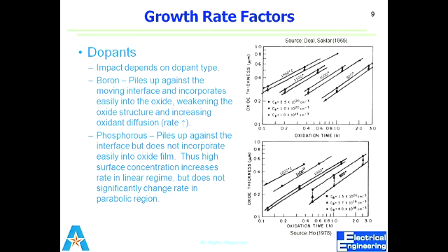In the case of dopants, you will find there are more non-bridging oxygen atoms. Let's suppose we have boron. It has 3 electrons in its valence shell, so it needs only 3 oxygen atoms shared with it. So one oxygen atom would be there with no sharing. Got my point? Due to that impurity, there would be more non-bridging oxygen atoms, so the ratio of non-bridging to bridging oxygen would be higher.